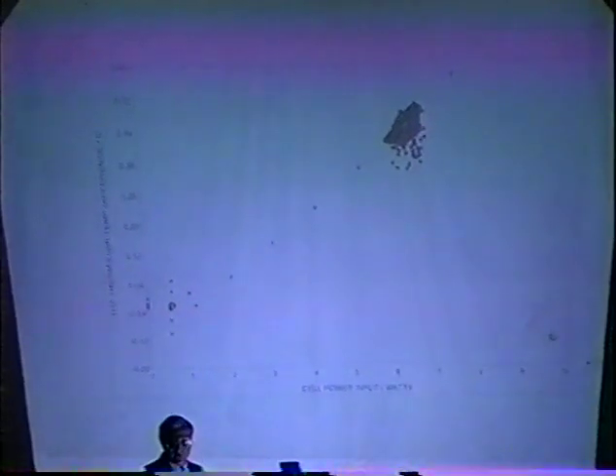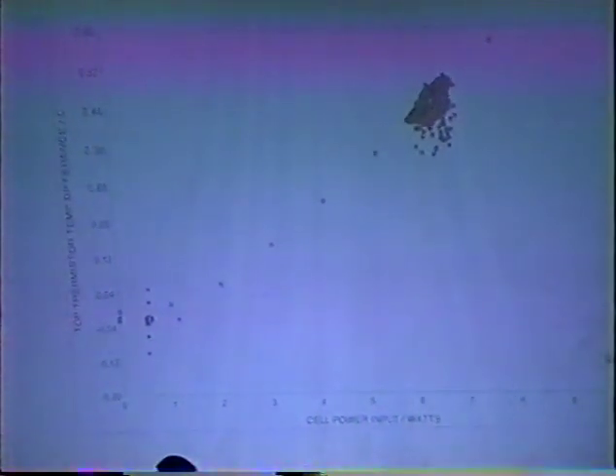In doing experiments, this is a typical result. You measure the top thermistor temperature difference versus that calibration curve. And for blank experiments, or experiments which show no excess heat, you expect to see a curve like this. All these negative points are due to the addition of solvent and the time. So those are non-steady state points. Basically, on these graphs, when you see concentrations of black, because there are so many points, this, for instance, has 32,000 points. Those are more in the steady state. So you get curves like that. You get curves like that for the lower thermistor set, the bottom thermistor set, the top thermistor set.